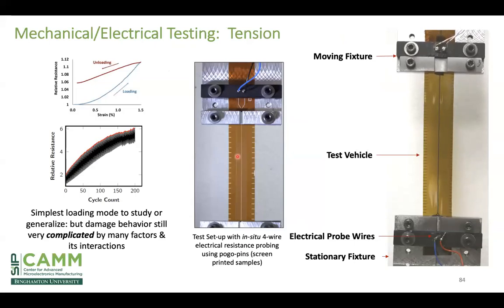In this case, looking at nano silver printed traces on a test vehicle, which we undergo mild strains repetitively while monitoring using 4-point probe their resistances. And you can see for a first loading cycle and then an unloading cycle, we develop a hysteresis and a lag due to the viscoelastic effect of the polymer substrate itself, and if there are any in an ink, which wasn't in this case, some there as well, and do this over many, many cycles and understand the evolution of how the relative resistance changes during this deformation process.